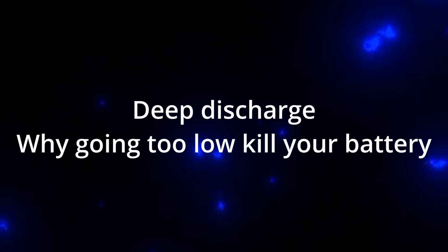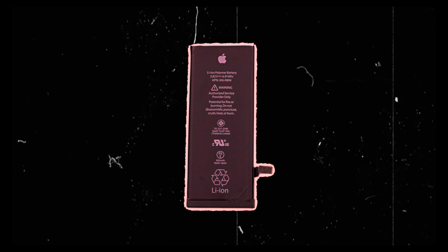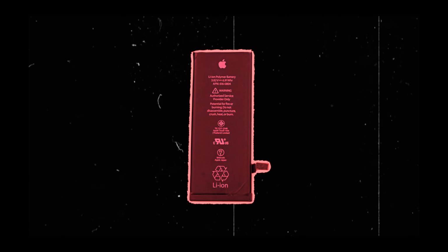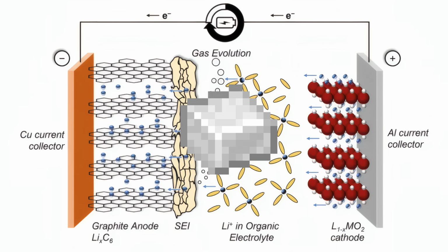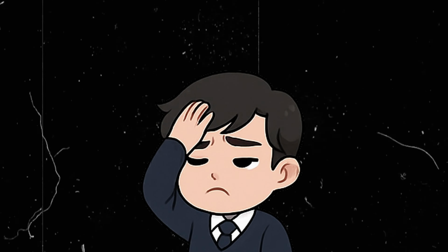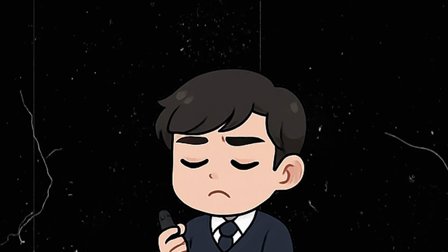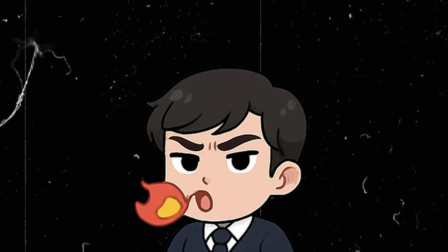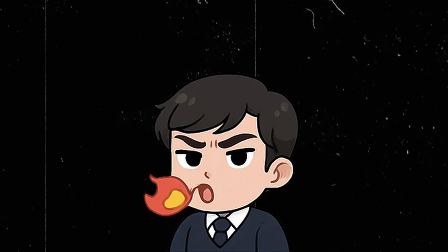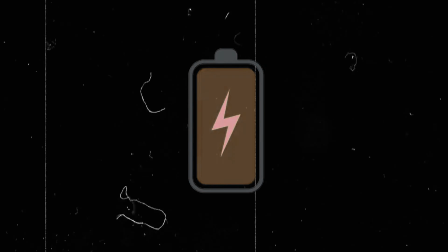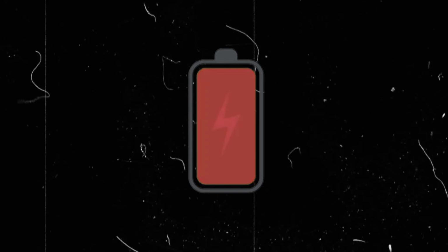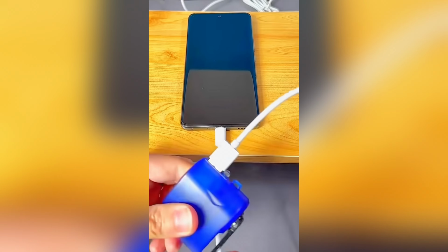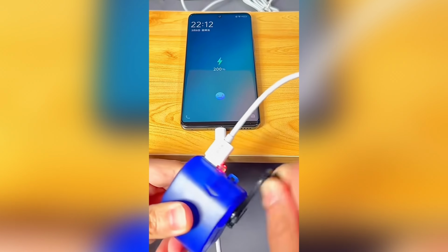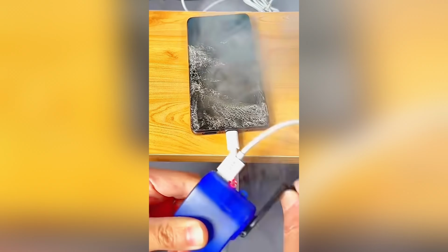Deep discharge, why going too low kills your battery. When a lithium-ion cell drops too low, things go bad. At this point, almost all the lithium-ion have left the anode, creating mechanical stress. The graphite layer expands and contracts, causing microcracks that damage the structure forever. If it goes too low, the copper collector inside the anode can start dissolving into the electrolyte. When you recharge, that copper can redeposit as a tiny metallic filament called a dendrite, and those can pierce the separator,